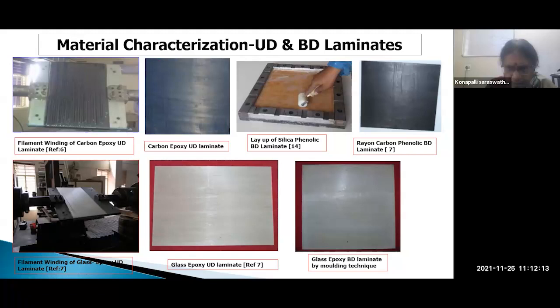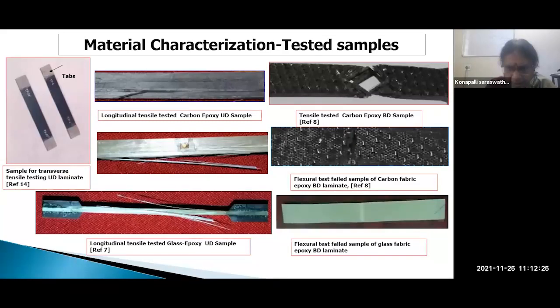Then physical properties we see to see the soundness of the composite, like volume fraction and density of the composite we measure. These are some of the pictures. I'm not able to take the cursor, it's becoming very difficult. So just you can see, these are the tabs, first figure. Then adjacent to that is the carbon longitudinal tensile tested carbon epoxy UD sample. Beneath is the glass sample. Then here flexural test bidirectional samples are there. Carbon epoxy, tensile tested carbon epoxy BD sample, and flexural test failed sample of carbon phenolic BD laminate and glass laminate. So this is how the material characterization is carried out.